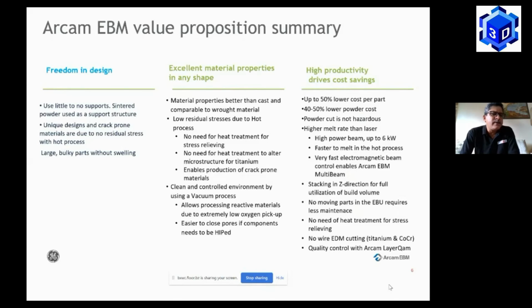So these benefits are realized in the case of a ARCAM EBM build process. Since the printing is already done in a high temperature environment, we don't require any further heat treatment process, which is essential to relieve the stress that builds up during the build process. Also, since the beam has a high melting volume and we could produce 3000 watts of power through the beam, you are able to build components dense and solid.